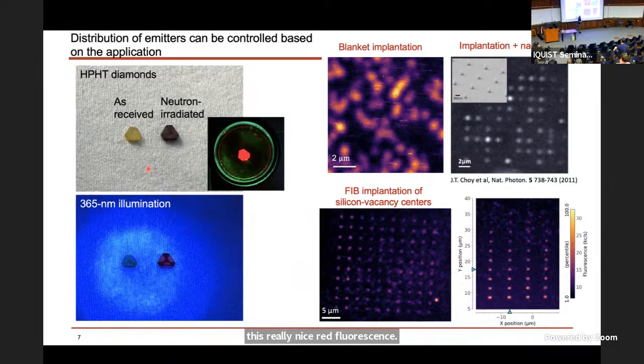You can also ion implant with nitrogen onto an ultra pure diamond crystal. Depending on the dosage, you get individually resolved color centers, and you can combine that with some kind of nanofab to isolate these defects. The bottom pictures are a couple of images of FIB implanted, in this case, silicon vacancies.